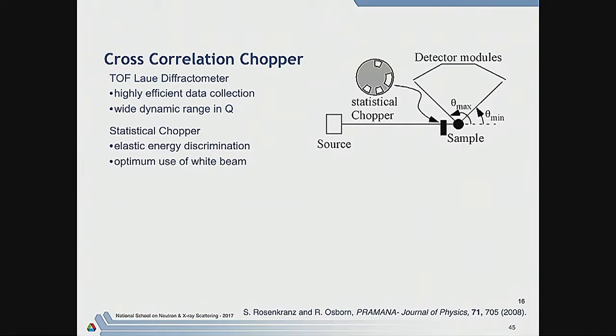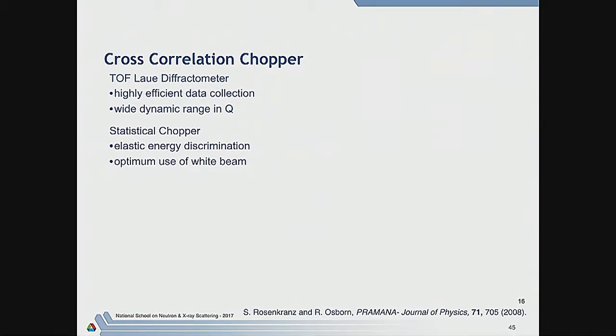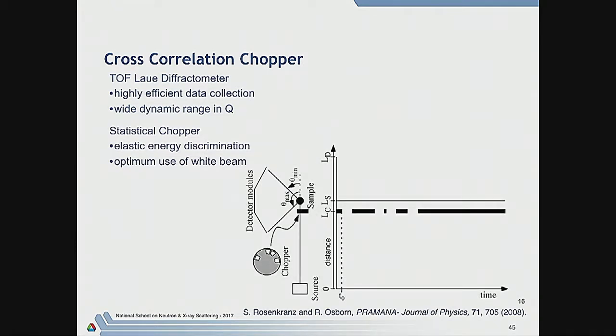Combine the efficiency of white beam Laue techniques with energy discrimination. And it turns out that if you go back to the literature of the 60s and the 70s, there was an awful lot of mathematical work done about how to use different types of modulated beam techniques, either Fourier techniques or using pseudo-random statistical choppers, to modulate a neutron beam. And these techniques became very popular in those days and were used in a number of classic experiments, but they've fallen entirely into disuse now for a reason I'll explain. But so here's an LT diagram, okay, which explains the principle of one of those pseudo-random techniques that is now utilized on CORELLI.